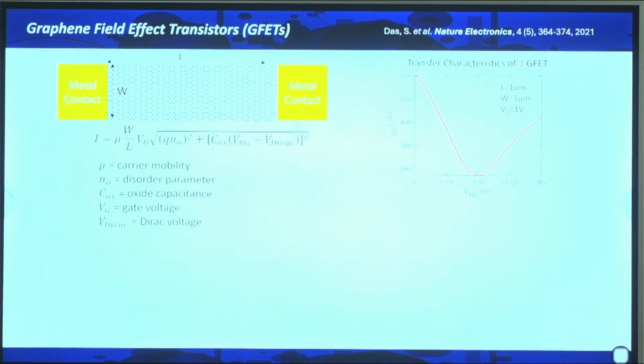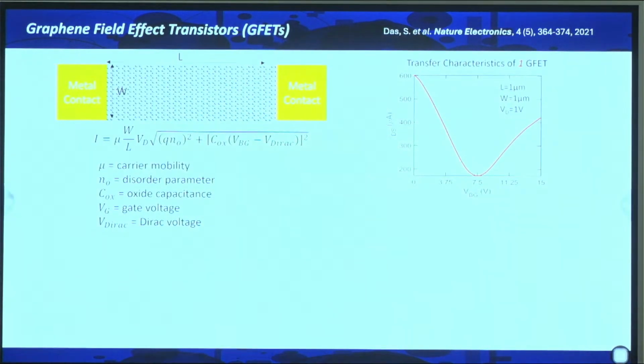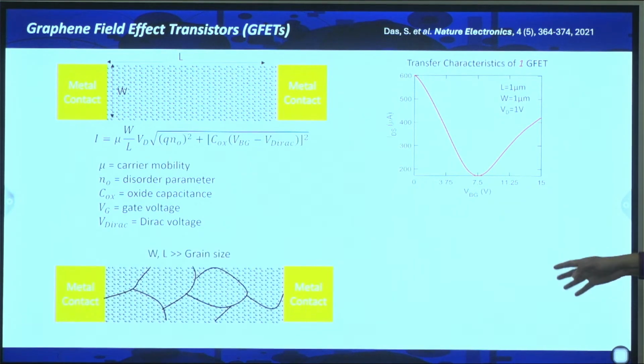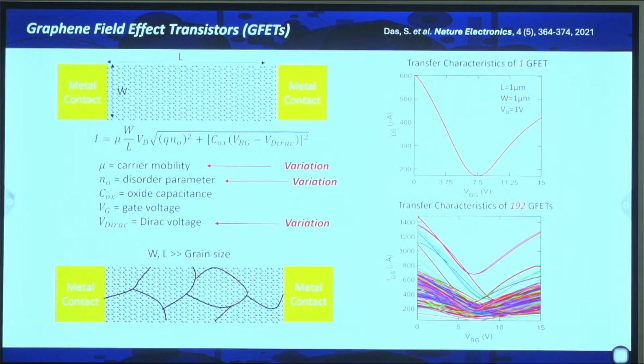So we have heard about graphene in this lecture quite a bit. We know this is how the IV characteristics of graphene look. And then as I told you, if you make graphene, and if it's CVD grown graphene, there could be a lot of grain boundaries in graphene, right? Because it's not a perfect single crystal material. Okay? And when you have a lot of grain boundaries, you cannot predict where the grain boundaries are going to be, right? So any material you make, it is very difficult. And then if you put two metal contacts and measure the current, not every device is going to give you the same response. And if you measure a lot of devices, look at the device to device variation, right?